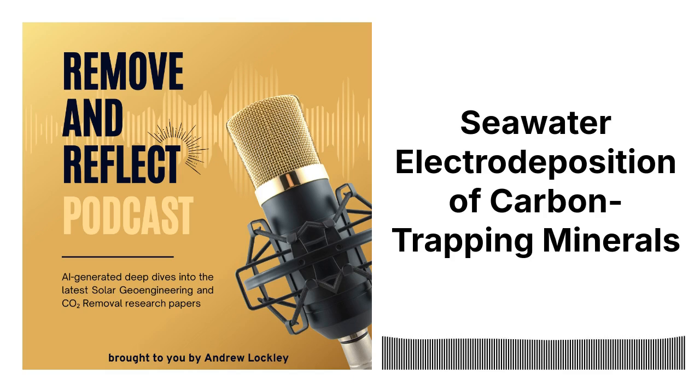So now the study also explored the possibility of growing these individual mineral particles into larger, more substantial aggregates, like something you could actually use as a building material. Exactly. So how did they manage to do that? Well, by carefully managing the electrolysis process over extended periods, they were able to grow centimeter-sized mineral aggregates directly onto the cathode. And what were the key factors in controlling that growth? Well, there were three main things they had to control precisely. The overpotential, which is that extra bit of voltage beyond the theoretical minimum needed for the reactions to occur, the flow rate of the CO2, and the continuous circulation of the seawater. That ensures a steady supply of the necessary ions to the cathode surface. So it's like providing a constant stream of building blocks for those minerals to grow.